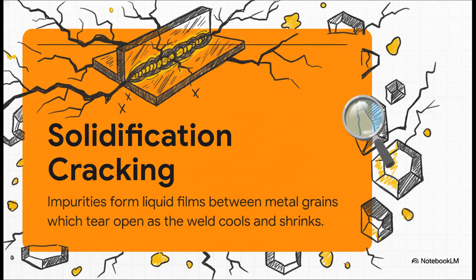So, with all that heat and stress, we come face to face with the #1 villain of this whole process, solidification cracking. See, as that molten weld pool cools down, little impurities, we're talking things like sulfur, can form these weak, liquid-like spots between the metal grains. Then, as the metal shrinks, all that stress just tears the weld apart from the inside out. It's an absolute nightmare and a catastrophic failure.